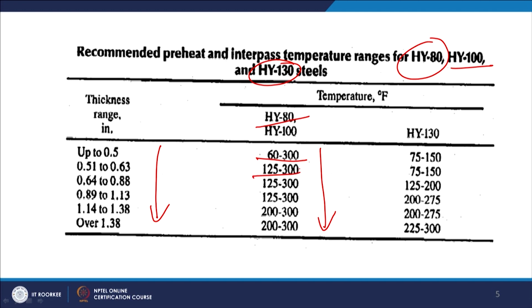So depending upon the thickness and depending on the welding process, the temperatures which are used have been mentioned here, and what it shows is that the minimum preheat and interpass temperatures will be increasing with the increase in thickness of the plate, while higher preheat and higher interpass temperatures are used for HY130. It will be offering us much higher yield strength as compared to that of the HY80 and HY100 type of steel. So, a proper combination of the preheat and the heat input is needed.